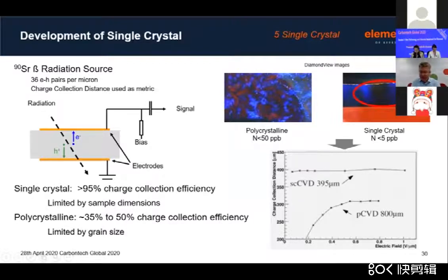And then secondly, when you calculate the charge collected, the charge collection efficiency can be very close to 100%, i.e. for every single particle that is captured and generates a charge within the diamond, you can actually see that charge and collect it and interpret that data. And as I say, the real key to that is the low defect density and also a very low nitrogen content, well below 5 parts per billion.